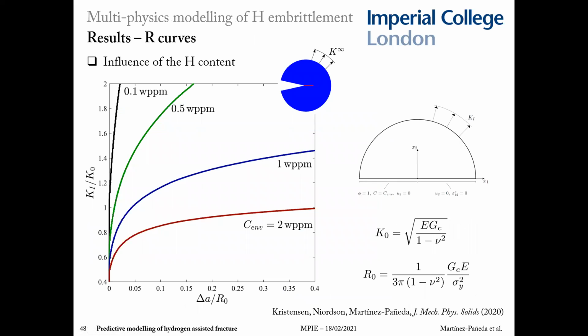So now let me show you some representative results obtained after coupling all the ingredients. So we have the microscale plasticity model, we have the mechanistic interpretation based on offline atomistic calculations, we have a rigorous treatment of the diffusion and the diffusion boundary conditions, and then we also have the phase field fracture to deal with complex cracking phenomena. So the first result that I'm showing here, these are R curves, so crack growth resistance curves. The applied K is in the y-axis, and then the crack extension in the x-axis. And as you would expect, the model captures how by increasing the hydrogen content, you bring down the fracture resistance.